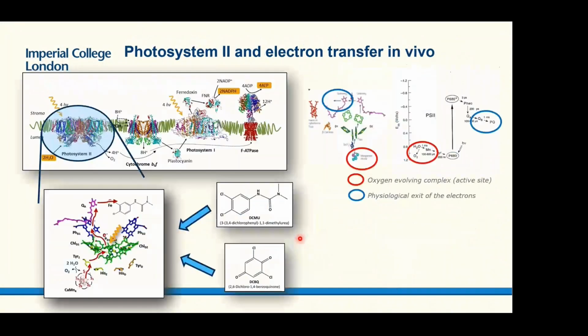One of the problems of the protein is that it normally lives in the membrane, and it has two phases, one where the electrons are moving and the other where the catalysis of water oxidation occurs. You can imagine it's like two enzymes joined together, the two phases of this enzyme. When you isolate the protein, it's more difficult to study the individual reactions, because if you are, let's say, using an electron acceptor that takes electrons from one side, the risk is that it goes to the other side and donates electrons to the catalytic unit.